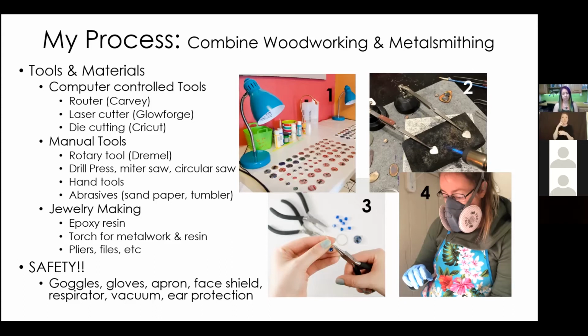So in this example, I have small jump rings that I'm attaching to a heart bezel. And it's really important to hold those jump rings in place with the third hand, just so the jump ring doesn't move around, but also to act as a heat sink. Because the jump rings are so small, a blast from the torch is enough to completely melt them. But because I've got them attached to the third hand, it helps with heat flow. So it disperses the heat a little bit more so that jump ring doesn't get overheated. So that allows me to effectively solder the two pieces together without melting anything into a clump, other than the solder, of course, that has to get melted.